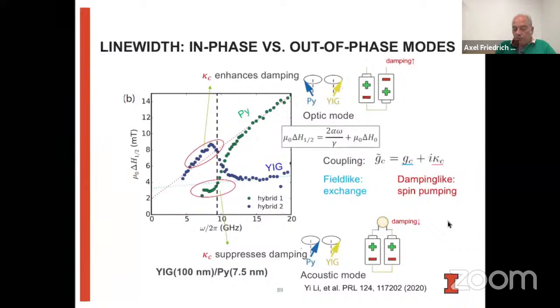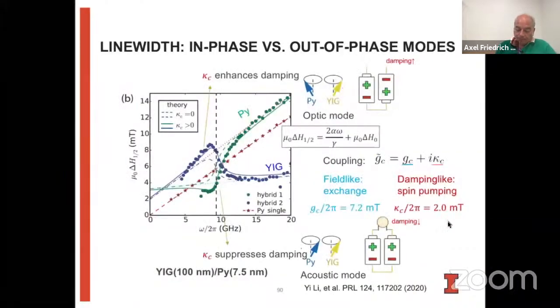So by thinking about this, we can easily identify the modes. Here, where the damping is suppressed, we have an acoustic mode where the magnetizations are in phase. The mutual spin pumping between these two modes will then reduce the damping overall, while this mode is the optic mode where the two magnetizations precess out of phase, and that leads to an enhancement of the damping. We can fit this to a theoretical model, shown here by these solid lines. If we don't take the spin pumping into account, we get these dashed lines where, as I said before, the line width is bounded by the line width of the individual modes, and you don't get line widths outside of what you expect from the modes on their own.